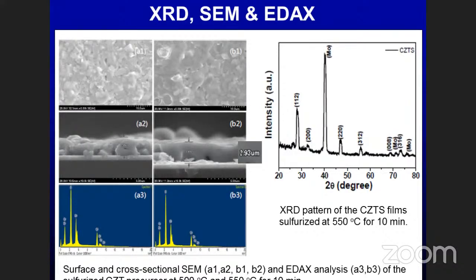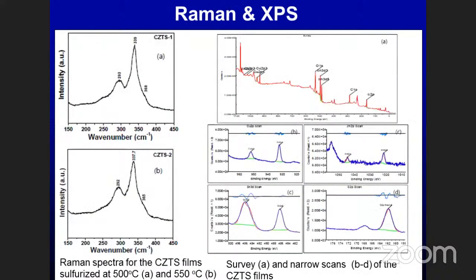And see that CZTS elemental analysis was done by the EDX. Okay, next one. Yeah, also we use some Raman technique as well as the XPS technique in order to detect the elemental analysis here. And see, this one is the Raman of the CZTS, where you can find the three peaks belonging to the CZTS from the Raman spectra, and here from the XPS we can easily detect the CZTS.